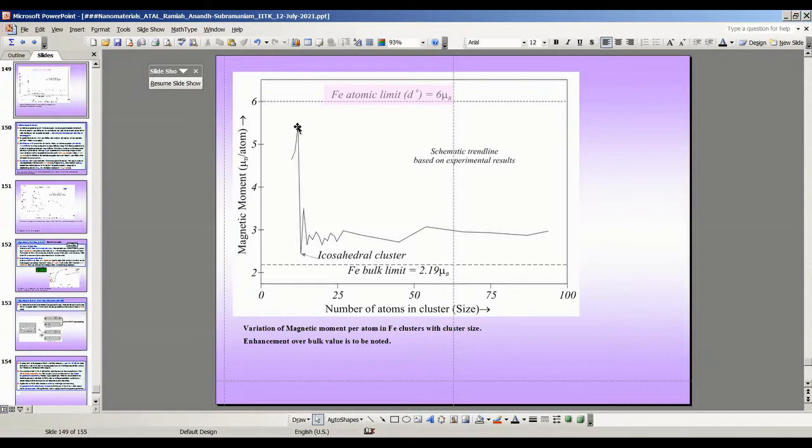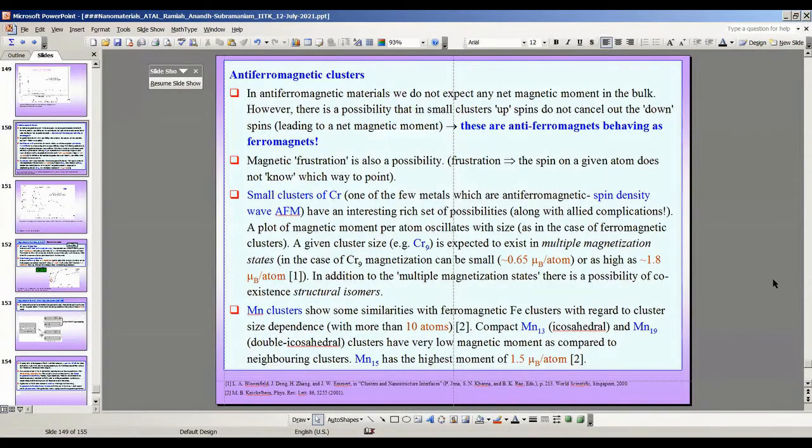But the important thing is that just add one atom and the magnetic moment changes so drastically in the small cluster regime. In the large cluster regime, now you can demarcate the small clusters and large clusters using magnetic moments. You see that the variation becomes smoother. But then it's still oscillating, and finally it slowly approaches that of the bulk. And that means that now I can produce a higher amount of magnetic moment, make it oscillate in the case of nanoparticles or nanoclusters.